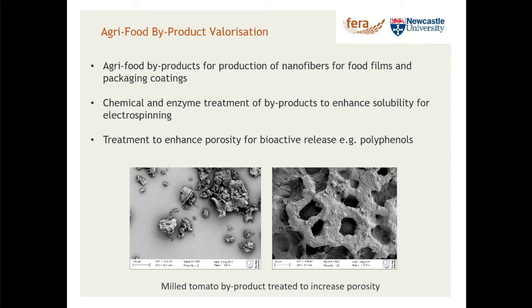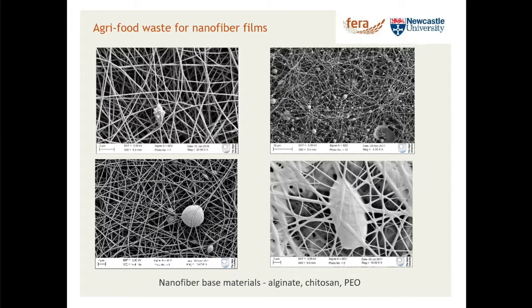So we started using this material and spinning with it to see what happens. And these are some of the sorts of films you get. So this is scanning electron microscopy, showing some of the sorts of fibers that we get. Typically, they tend to be randomly orientated, although that is something that can be controlled if you really need to. And in this case, this is little bits of milled micronized tomato skin sitting within, in this case, an alginate, seaweed-derived, if you like, matrix.